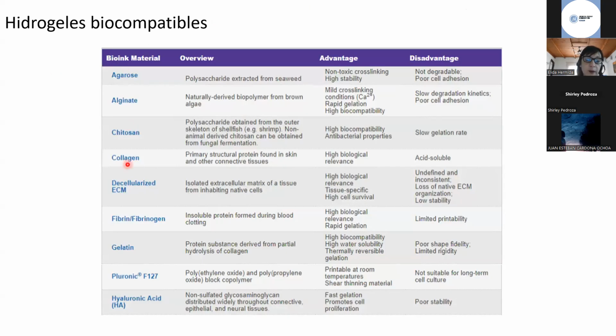What kind of hydrogels can we use? We have a very large list of different hydrogels. Some of them have advantages and also disadvantages. Sorry, this is in Spanish, but you can understand, of course. Usually our hydrogels are not just one material but a mixture or blend of different materials. For instance, we are working nowadays with a mixture of alginate, a material with a mild cross-linking condition through the incorporation of calcium ions. It has very high biocompatibility, but poor cell adhesion. Since it has poor cell adhesion, we mix in a little part of hyaluronic acid. Hyaluronic acid promotes cell proliferation, but has poor stability.